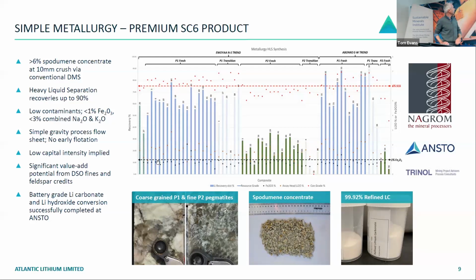And importantly, we also look at our iron concentration within that concentrate. You want that iron to be below 1%. The higher that iron is, it's a problem for the converters because it actually starts to form a slag within the kilns. So every couple of weeks, they need to stop the kiln, scrape off all the slag on the inside of the kiln, and then start the plant up again. So they don't want to see iron in that concentrate at all. And the lower that is, the better your concentrate.